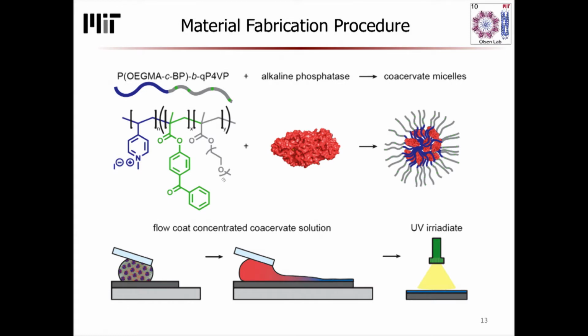We used an apoenzyme, alkaline phosphatase, which has high catalytic activity in the presence of zinc and very low catalytic activity in the presence of all other heavy metals. This basically gives you a sensor selective just for zinc in complex metal mixtures. We coacervate this, we flow coat it using simple industrial processes, and then UV irradiation for about 60 seconds immobilizes the film by cross-linking the benzophenone, so everything becomes insoluble in water.